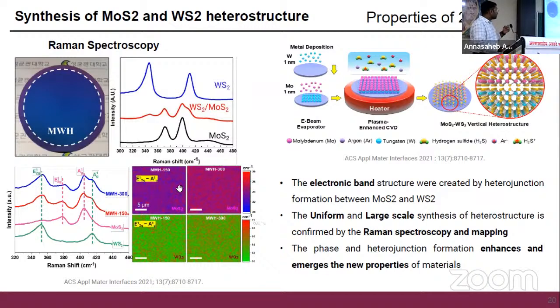Typically using Raman, we also did Raman mapping. Using Raman, we can map some area, and then using that area we can map that image, and also calculate a few parameters, such as the distance between these 2 peaks, which gives us knowledge about how many layers are present there. Depending on this calculation, as shown here, we can calculate the peak difference, and from mapping those regions we will know how uniformly our material has synthesized. If the peak difference is too much, then we will see too much variation in the mapping region. In order to confirm uniform synthesis, we use this Raman technique to confirm this uniformity.